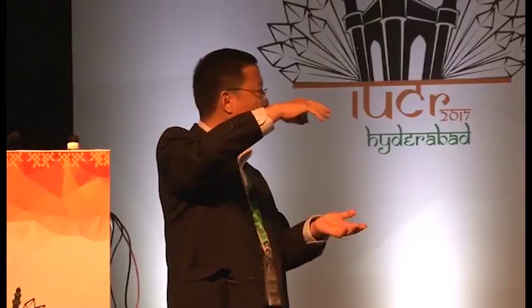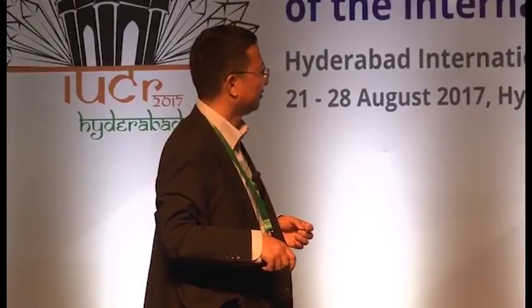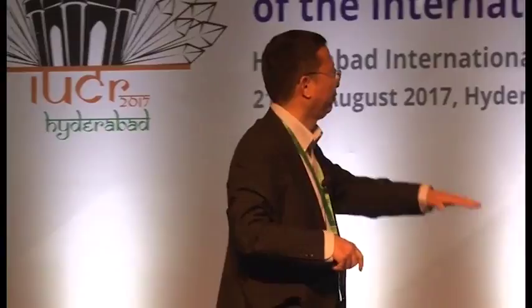And we just use a COT and Cp*. The Cp* can be replaced by other ligands, anionic pi-bond ligands. For example, here we use borabenzene. For the borabenzene we use different R groups and get a series of compounds. For them, we keep the COT unchanged and replace Cp* with borabenzene with different substitutions.